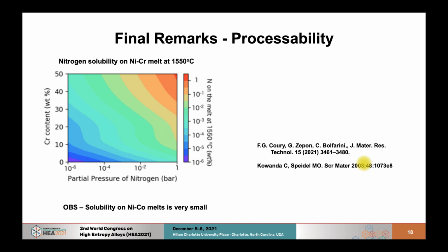One final remark I'd like to make is regarding processability. One thing we think is very critical is to report the content of interstitials in these alloys, and we show this on this curve that basically shows the nitrogen concentration in a melt at 1550 degrees Celsius versus the partial pressure of nitrogen and chrome content. Basically what this is showing is when we increase the chrome content, the nitrogen solubility spikes up orders of magnitude in the melt.